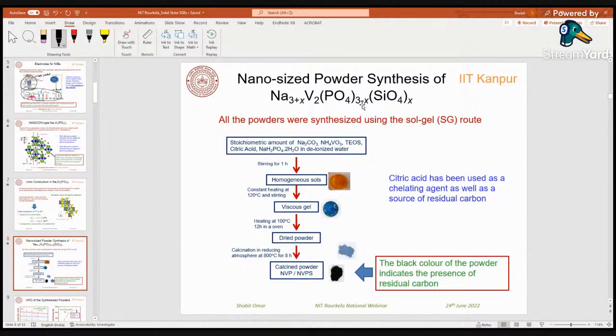Okay, so we tried to synthesize the nano-sized powder of NVP doped with silicon, and different compositions are prepared, and these are prepared by the sol-gel route. The process is already shown here. We have used citric acid as a chelating agent, and this citric acid not only works as a chelating agent, but it also provides residual carbon inside this material that will increase the electrical conductivity of this material.